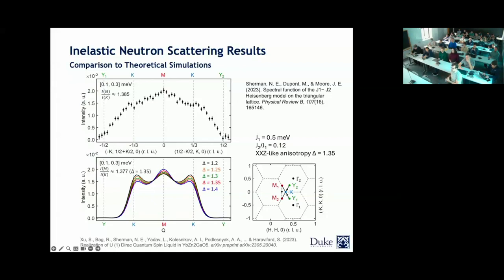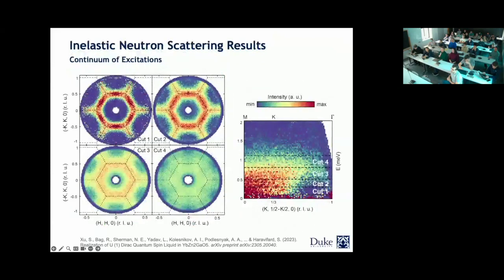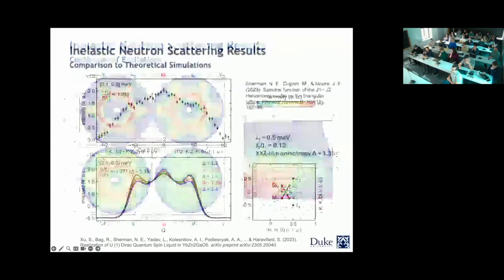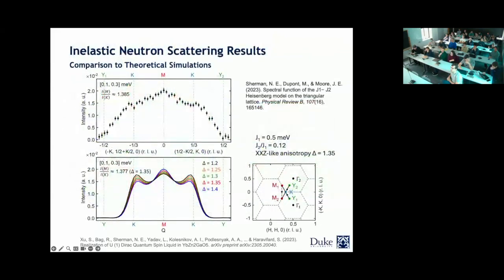So here what I'm showing you is the intensity as a function of Q for the neutron scattering data. The reason that I made this cut, so it's practically making a cut across here, okay? So it's picking up at the endpoint. The reason that we did this cut and started analyzing it was that Jules' model was for isotropic systems. We already know that our system is anisotropic. So when you have an anisotropy, we started to think of how we can implement the anisotropy parameter, which would be delta, into the model.